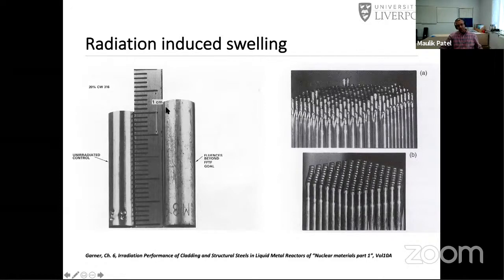You can see that there is a macroscopic growth in length, and this has almost nothing to do with the fact that it's heated, but everything to do with the radiation-induced void swelling that you can get. Now imagine that the swelling is on an atomic scale, but imagine that happening all along the 4-meter long rod, right? And there are 50,000 of these rods that undergo this swelling. From a simple reactor physics perspective, the flux of neutrons is very well controlled. They want the flux of neutrons to be uniform along a certain length of these rods. And when you change the length of these rods, the neutron flux profile fluctuates in the reactor. What that means is that the reactivity of the reactor fluctuates, which means your operation is no longer going to be as stable as it was.